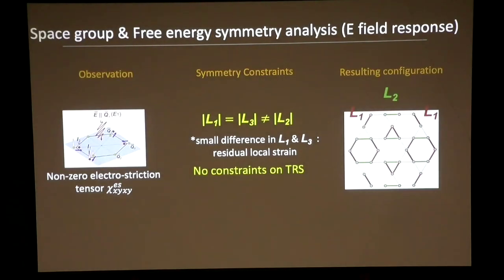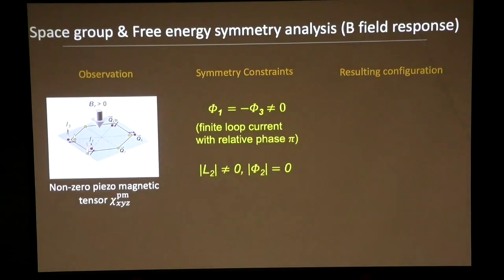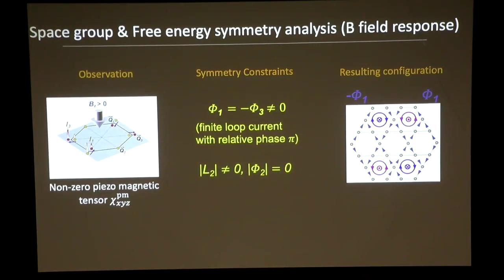So we worked with our theory collaborators, and they were able to write down a simple Ginzburg-Landau expression, which follows the symmetries of the system. And you can show that our two experiments, the electrostriction as well as the piezomagnetism, impose constraints on the possible CDW. The electrostriction tells you that you should have these three bond orders where one is different from the other two. And the magnetic field of piezomagnetism also imposes constraints, and it tells you that you should have loop current orders that look like this.